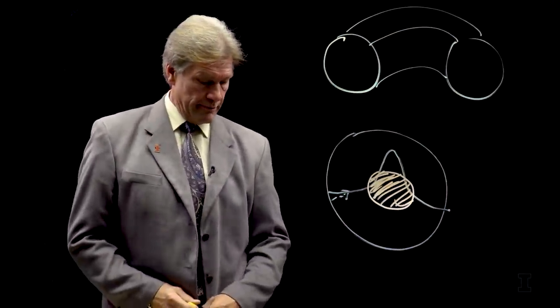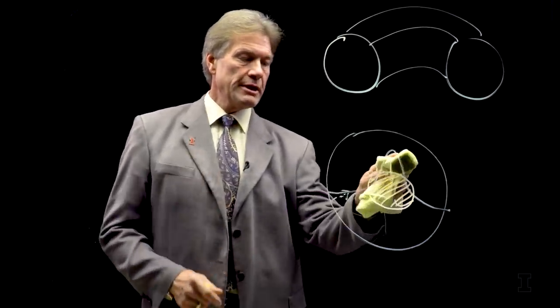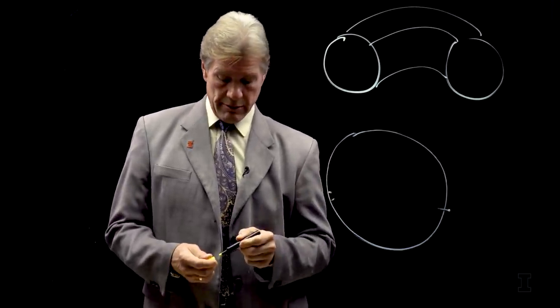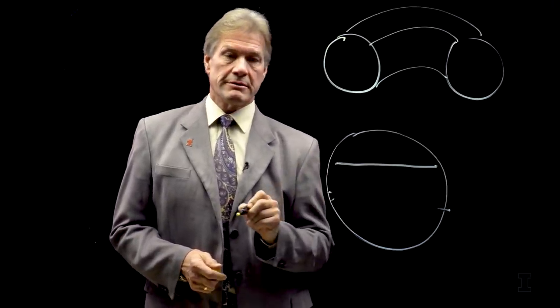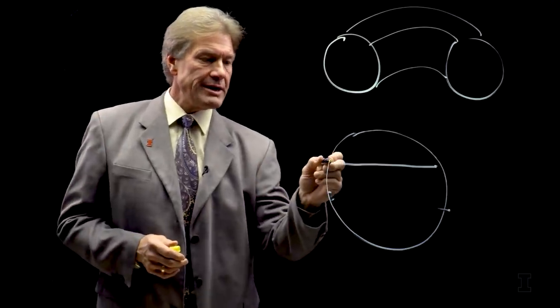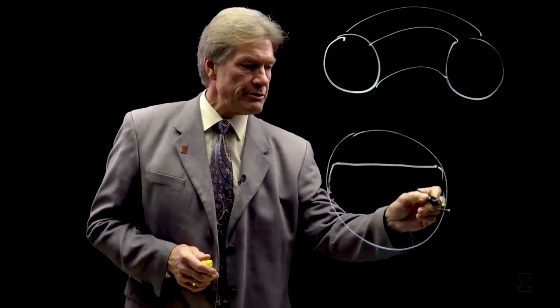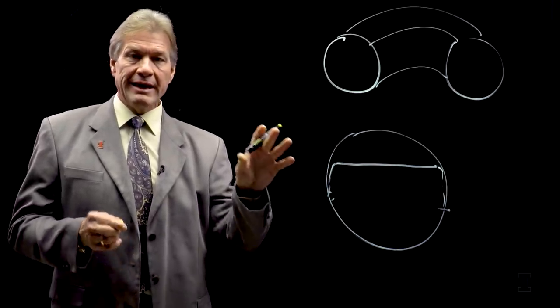Now, let's say I have lithium walls. So here, I don't have the cold return flux. And because I don't have the cold return flux, there is no cold coming back. So my temperature profile can be flat. I can be hot all the way across. Yes, there's a plasma sheath, very, very small near the wall. But basically, my entire volume can fuse. All of this becomes something that can participate and make fusion reactions.